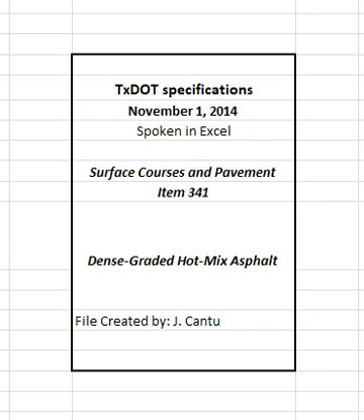Investigate density profile failures and take corrective actions during production and placement to eliminate the segregation. Suspend production if 2 consecutive density profiles fail unless otherwise approved. Resume production after the engineer approves changes to production or placement methods. Table 15. Segregation, density profile, acceptance criteria. See table in specifications.